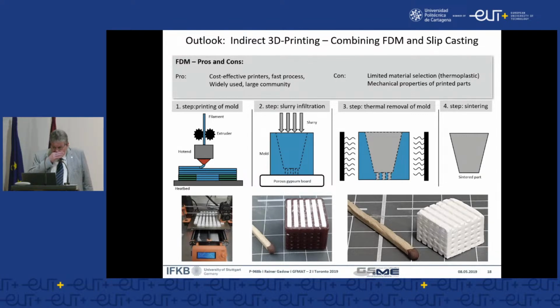And Esslinger's concept was unique. He said, I will not make the structure of bioceramics directly with that technology. I use it for the mold. And then the mold is my negative. In this porous open structure, we fill the ceramic suspension, the so-called slurry, let it coagulate and dry, and then we remove the mold. The mold is a lost mold for each component. And by the way, he did achieve such a perfect rectangular structure.